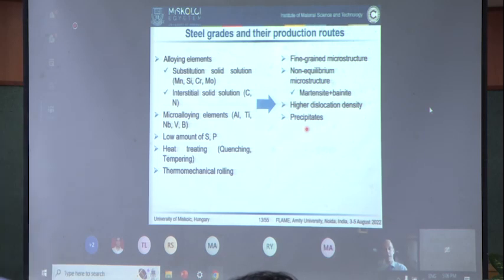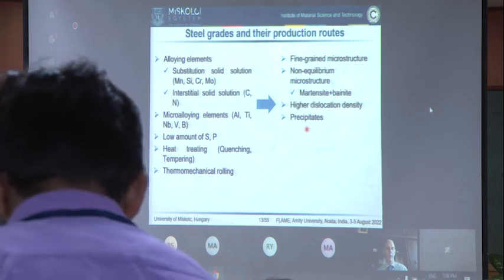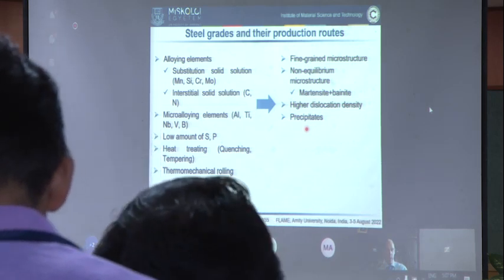Especially in the quenched and tempered group, we can find boron in order to increase the hardenability, the so-called quenchability, of high-strength steels. The steel producers generally focus on reducing the sulfur and the phosphorus content in order to have high toughness in these steels. And they are also using, as I mentioned before, heat treating and thermomechanical rolling.